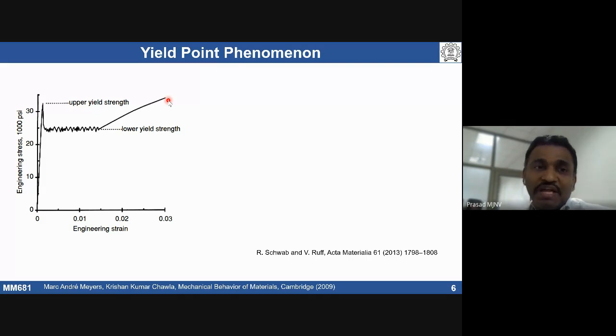It was reported around 1840, 42. The first observation was that this kind of stress strain curve is not a smooth flow curve. Initially there is elastic deformation. After some amount of stress, there is a drop in yield stress. This sharp yield drop has been observed in a certain class of materials like steels containing very low carbon or low nitrogen content. After the drop, there is almost constant stress with slight serrations in the stress strain behavior. After a certain amount of strain, it follows the regular trajectory of work hardening nature.